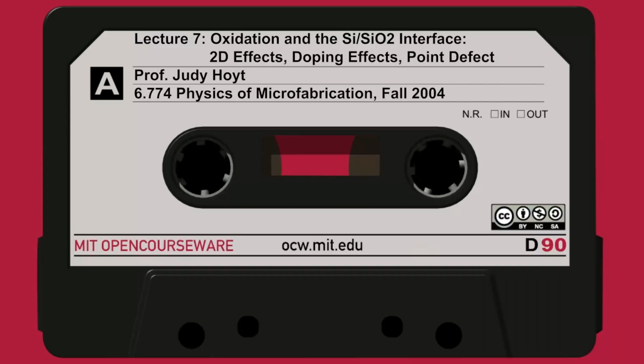So it's not a complete layer that goes all the way throughout the crystal, but it doesn't belong there. But I can grow this fault. I can make it longer within the crystal by adding extra silicon interstitial atoms, people believe, on either edge of it. So stacking faults, people use their growth rate as a measure of the injection rate, or the injection of silicon interstitials, if they grow or shrink.